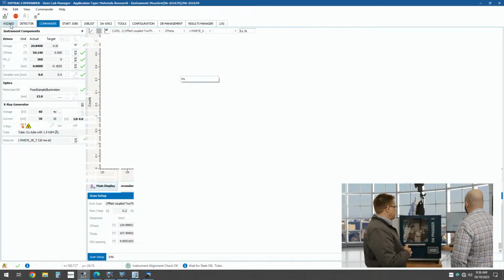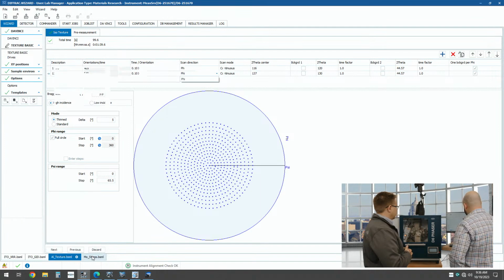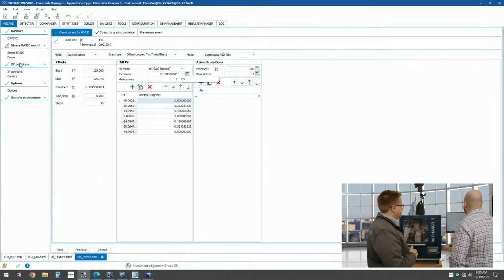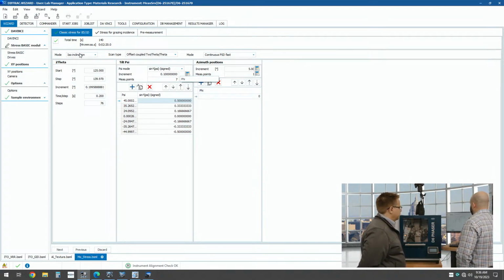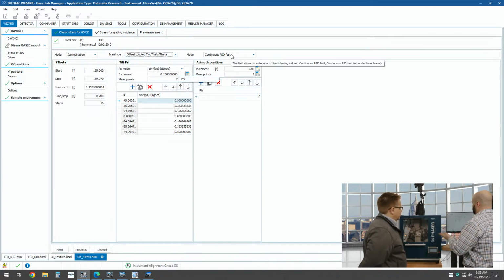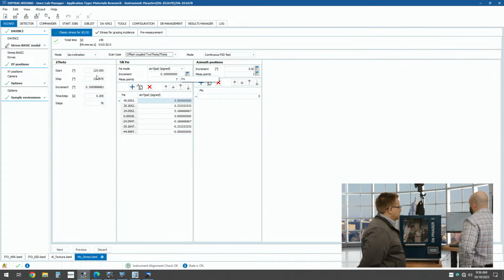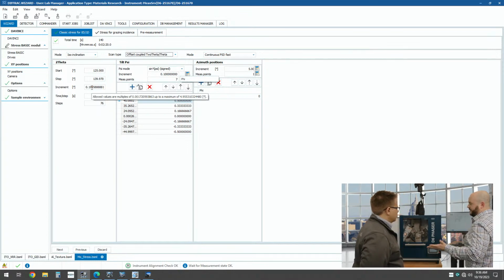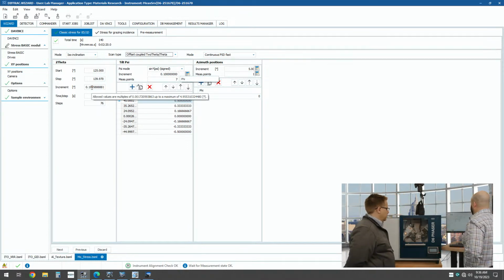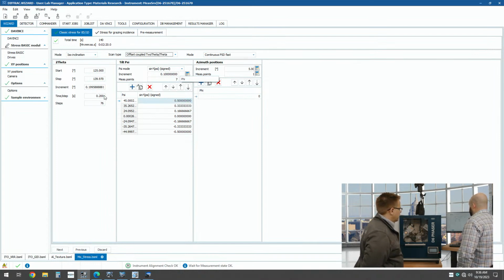Now, I'm guessing that you've set up another wizard? I'd be happy to share that with you. All right, great. We'll go ahead and switch to the computer. So moving over from texture, you can see, again, I already set everything up in DaVinci, very similar to what I had for texture. In this case, the detector is fully open, and now I'm just doing, you can see, ISO inclination here, offset coupled 2 theta. So it's a continuous scan from 125 to 140 degrees. Okay. Pretty large increment because these are typically strained materials with very broad peaks. Yep. And collection time 0.2 seconds.